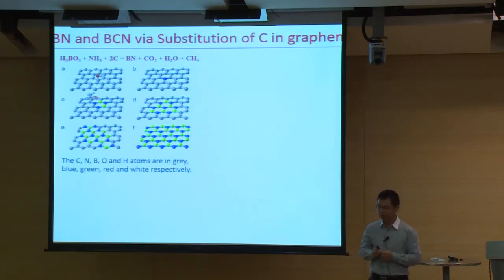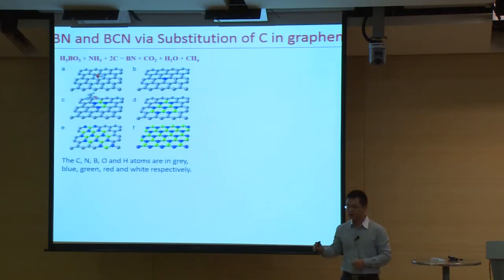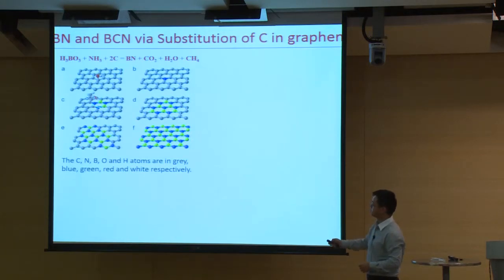Okay, so this is the final story in the BCN system. As you already know, the lattice constants of graphene and boron nitride are very close, with a mismatch of only 1.8%. So is it possible to convert graphene to boron nitride using a substitution way? Here we start with CVD graphene, and then we use boric acid as the source of boron, and ammonia as the nitrogen source. At high temperature, the carbon atoms are substituted by nitrogen and boron, and finally we can get a fully converted boron nitride.